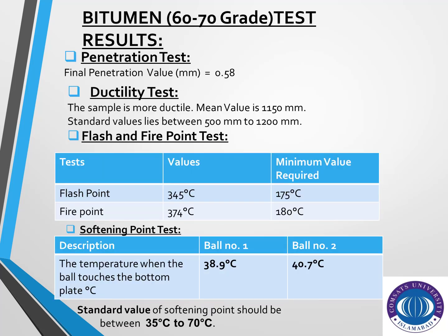In the Los Angeles abrasion test we get a value of 29.7%, and the standard value should be less than 30%. Here is the bitumen test showing some results, and we get a penetration value of 0.58 millimeter. The penetration test is basically used to check the grade of the bitumen, and we get a grade between 60 to 70. The ductility test is used to check the adhesive property of asphalt binder.